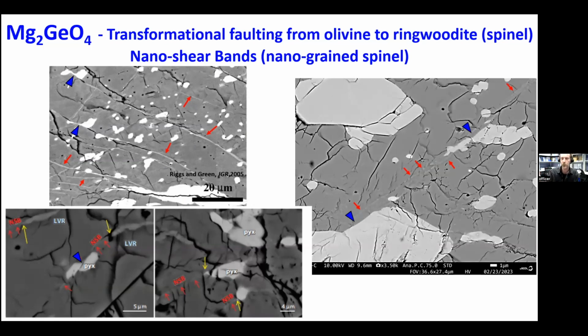And I should mention too, the idea was that the anti-cracks and these bands, the spinel is nano-grained, so the grain size is so small that it can't support shear stress, and that's why they act similar to cracks or to shear planes. And you can notice too, these white grains that are kind of glowing, these are like germanate pyroxene, and you can see that when these bands pass through them, they actually shear the grain. So you have shear localization happening on these bands, and you can see this here. And then here you see a long band, which is in red, and it's shearing this grain, and then possibly shearing this one as well, these blue arrows.